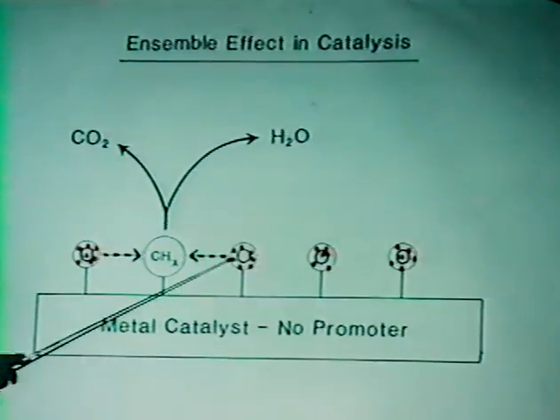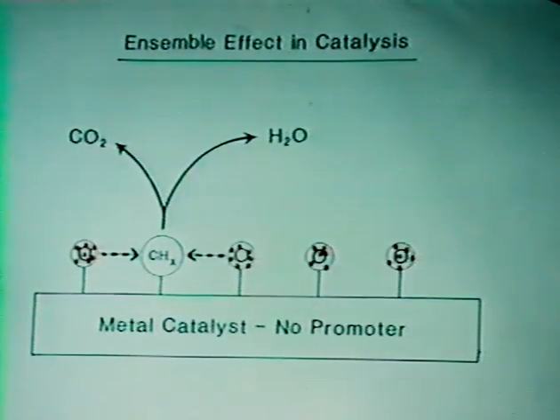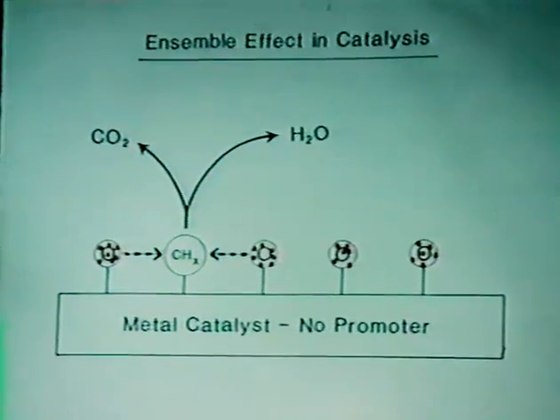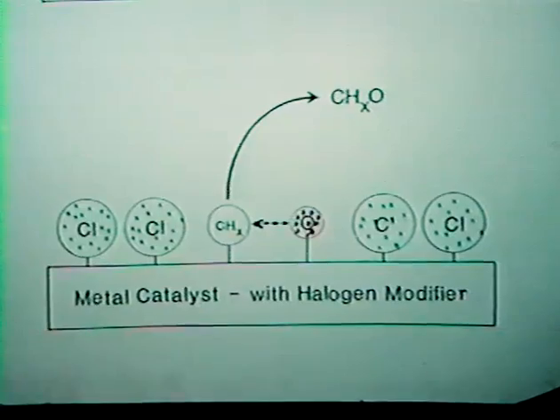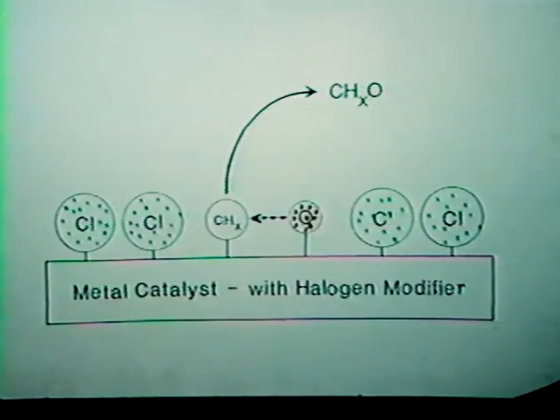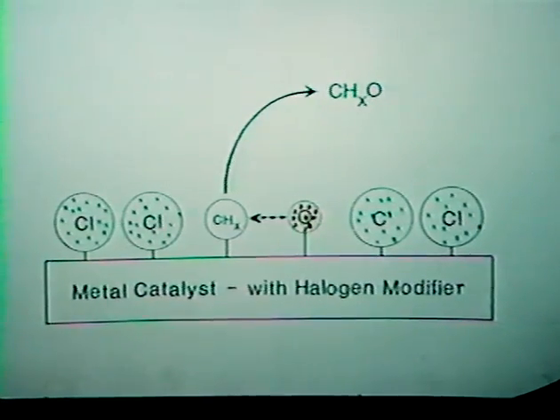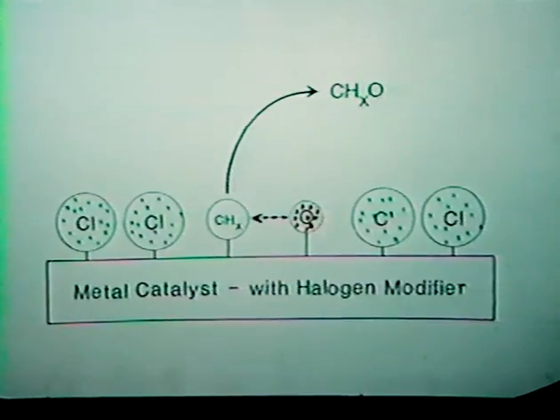Well, the thing that occurs to everybody who reads catalysis literature is ensemble control. If you can take a, let's say, carbon or CHx fragment, which has plenty of oxygen neighbors on the palladium surface, then the result of oxidation is going to be carbon dioxide. And if you block the sites so that only one neighboring oxygen will be available to carbon, then you're going to have lower oxidation products. In our case, we're concerned for a moment with carbon monoxide. And the halogen modifier, and I'm bringing coal to Newcastle when you talk about halogen control, it's in ethylene epoxidation.